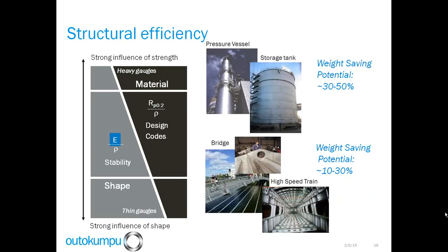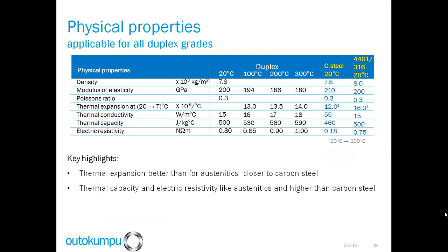When we consider structural applications and potential weight savings, specific strength applications where there's a strong influence of strength, such as pressure vessels, storage tanks, and piping systems, this offers the best opportunity to use thinner gauge duplex products. If we're looking at specific modulus applications related to the stiffness to weight ratio, such as beams and columns, we have less of an opportunity for weight savings in those types of applications.